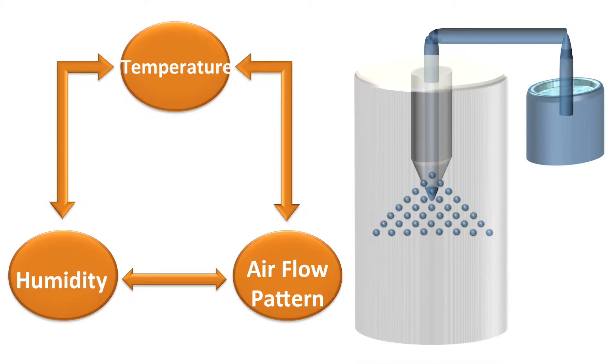So for that purpose I need to control the drying process of each one of these tiny droplets. For that I put the spray into a container — a cylinder container — in which I can control the temperature, the humidity of the air that comes in as drying air, and also the flow pattern and flow speed of the air entering the environmental chamber. By finding the interrelation between these three factors, I can provide an ideal environment for these tiny particles to dry out and give us fast but not furious drugs — more efficient and effective painkillers at the end.